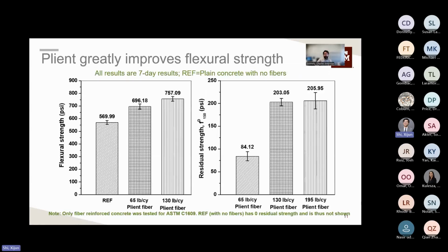A key area that Plient offers benefits in is the flexural strength. As we know, concrete often fails in either flexure or tension, and for many elements that are used in construction, such as slabs or beam elements, the flexural strength is the critical parameter that we look at. Here are some results from 7-day testing using 1609 beam tests. On the left there, you see the flexural strength test results. And on the right, you see the residual strength, the post-crack performance.